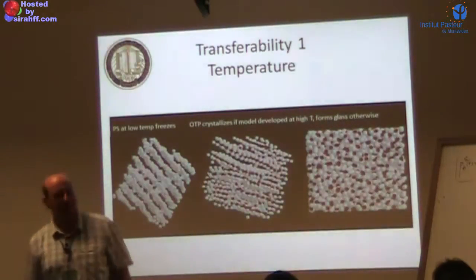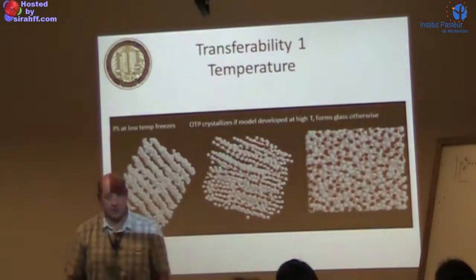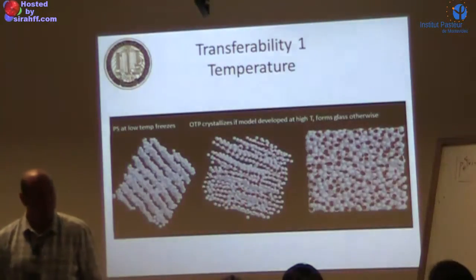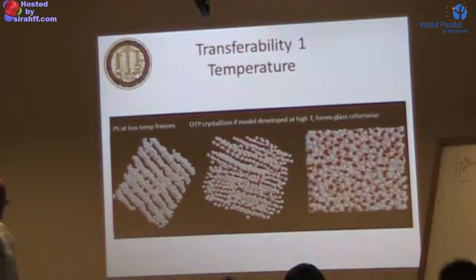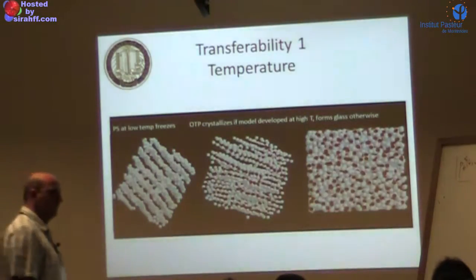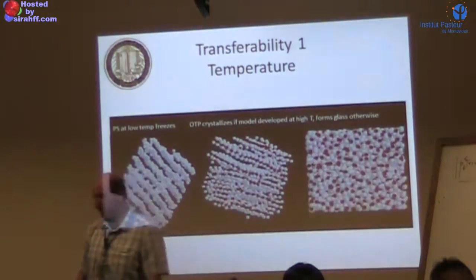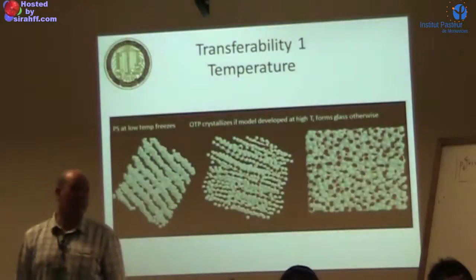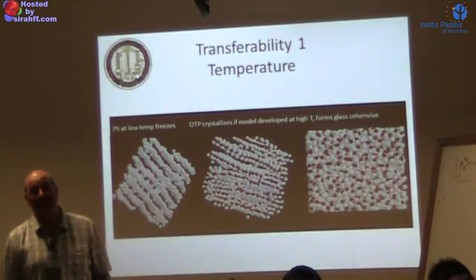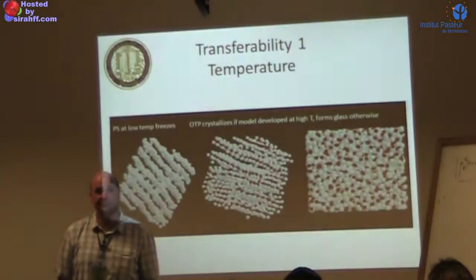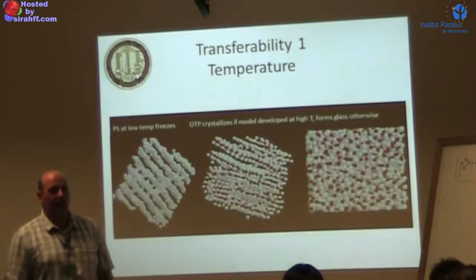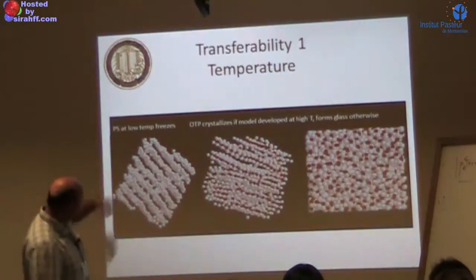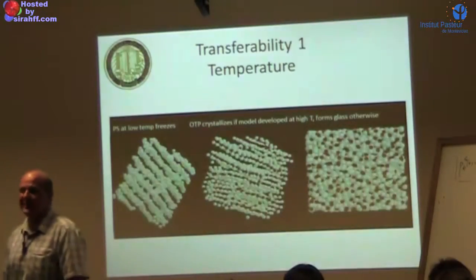Let's talk first about temperature. This slide shows two examples. On the very left is polystyrene, optimized at 450 Kelvin compared to the melt, and then cooled down to around 315 K — which takes polystyrene below its glass transition. What you see, for all purposes, is a polymer crystal. So polystyrene crystallized — it doesn't work.